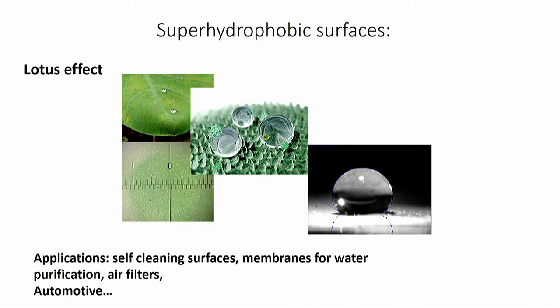The state of the art in this field is that we are able of doing very nice superhydrophobic and superamphiphobic surfaces, that is hydrophobic and also repelling for grease, but in the laboratory. And these very nice surfaces are very delicate. It won't stand in real-life application. So all this is made by making a rough surface with nanostructures on many scales, and these very nice nanostructures won't stay there forever, but would probably be taken away just wiping the surface. So this is the state of the art.